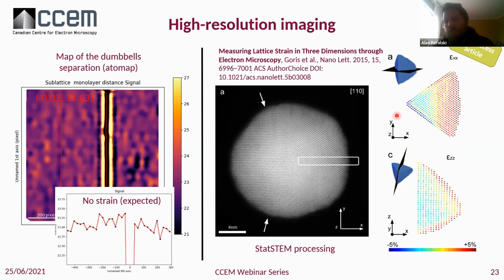Here, just to show that you can have some strain using this type of method, I put an example that is using the StatSTEM process on a nanoparticle. This is an open access article, and I recommend reading it. This is the type of result that has been optimized, really pushed to the limit, so the amount of work to do that is probably huge. This is a 3D atomic reconstruction of this gold nanoparticle, and then they took different sections of it and measured the strain using this type of real space approach.